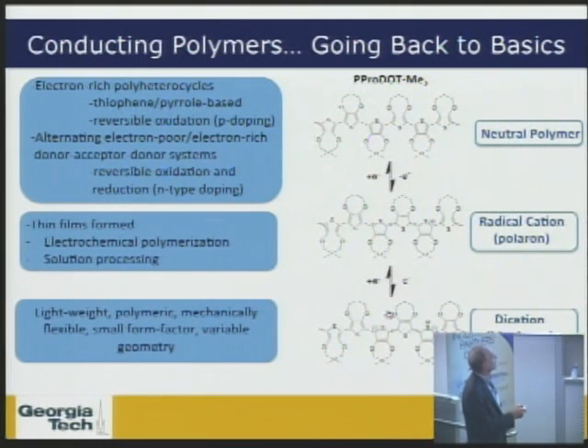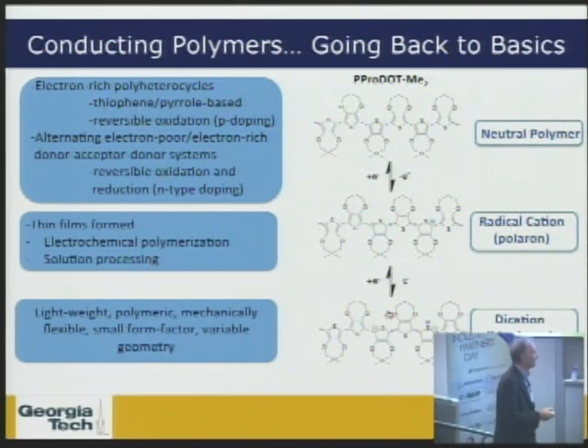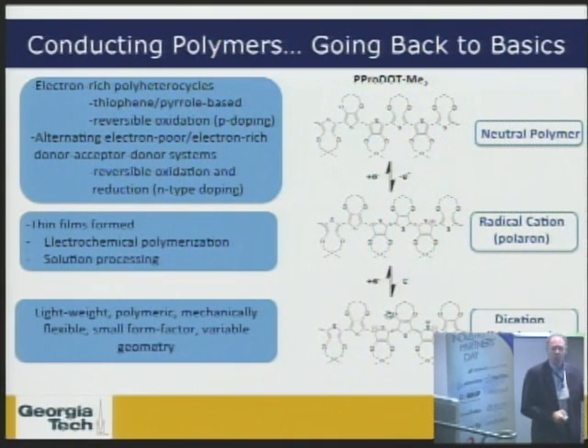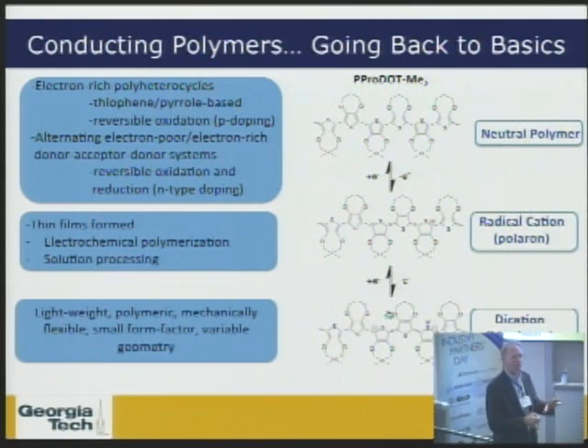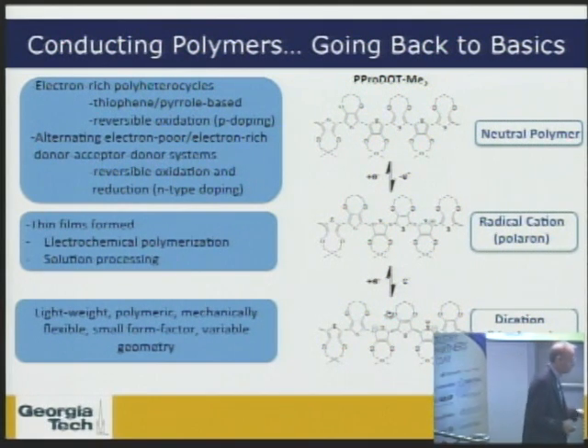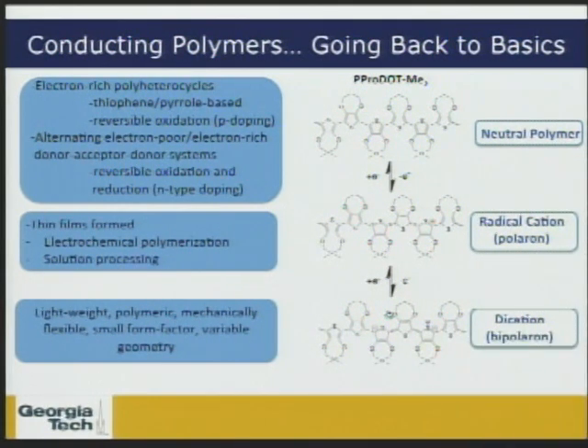And then there's an electrochemical oxidation of that material or a chemical oxidation of that material in order to form a delocalized cation radical and then ultimately a dication, a so-called polaron or bipolaron, that give these high levels of conductivity. And what's especially important as we think about taking these materials to the next step, as polymeric materials, they're lightweight, solution processable, mechanically flexible. And as we think about how we can put them into various kinds of applications, we can think about the form factor of those applications, and I'll talk about that a bit when I talk about capacitors.